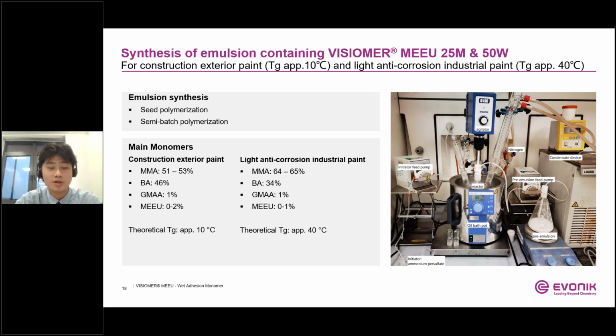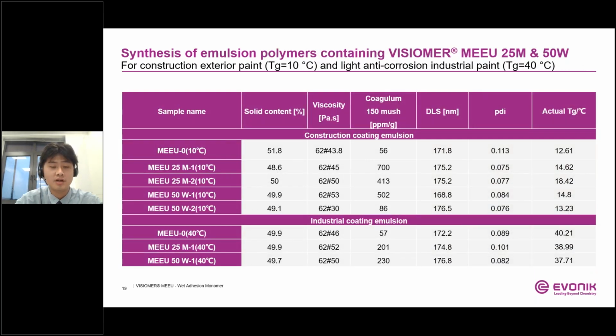And based on the previous experiments, the addition amount of MEEU was optimized to 0 to 2% and 0 to 1%. To better control the particle size, we changed the process to seed polymerization, which means using a seed to replace the self-nucleation. And here comes the analysis part. According to the analysis, the particle size by DLS was well controlled through the seed polymerization, and the solid content and viscosity were quite stable this time.